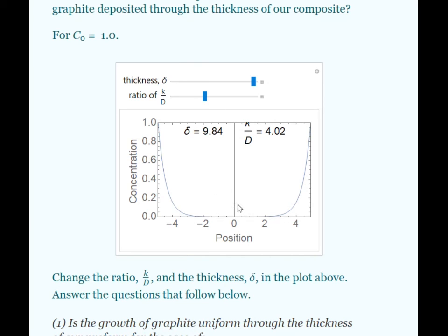And what this means is that the diffusion of acetylene into the surfaces is too slow to get into the middle, and it gets deposited completely before that happens. So this is a bad situation for any kind of reasonable thickness of this composite, because the center will be porous and the outside edges will be dense, and that's not what you want.